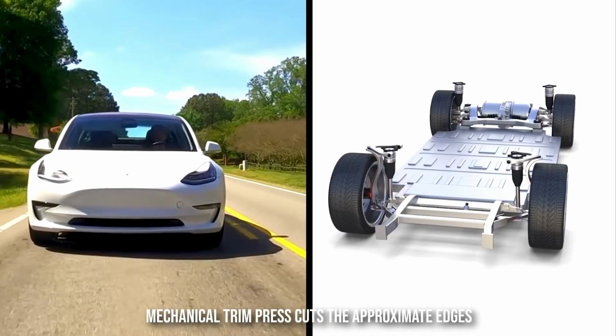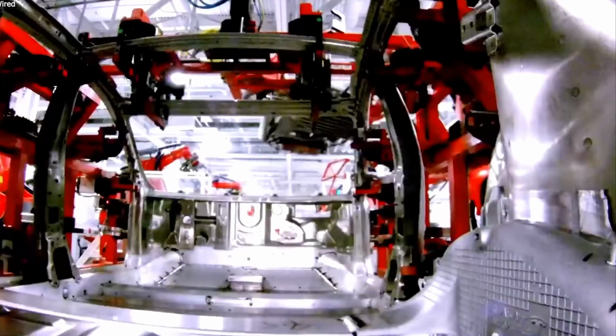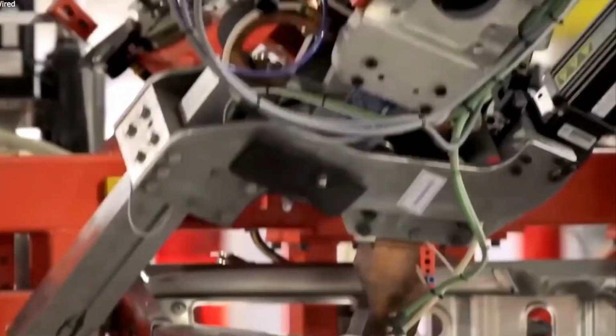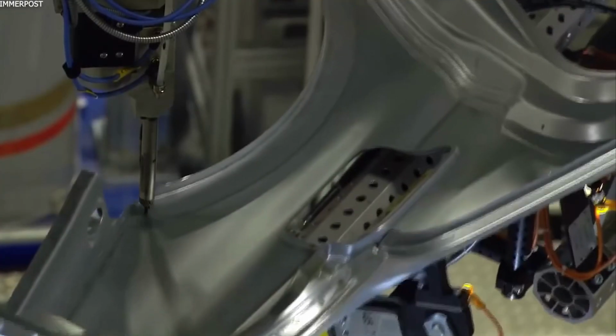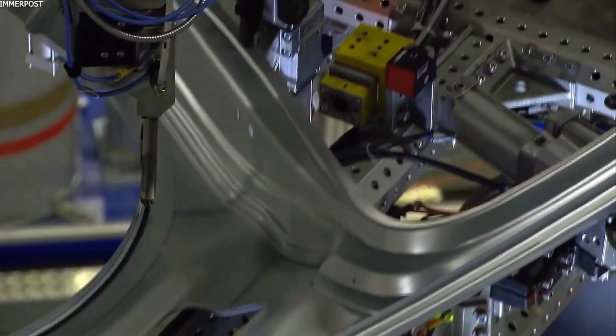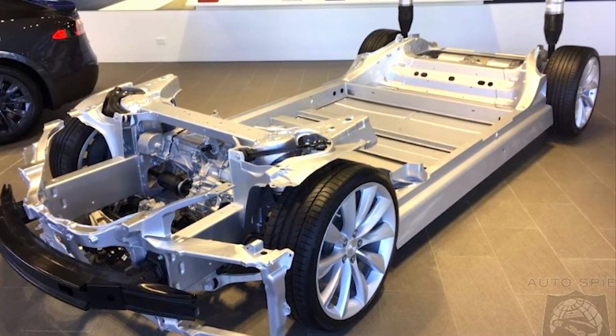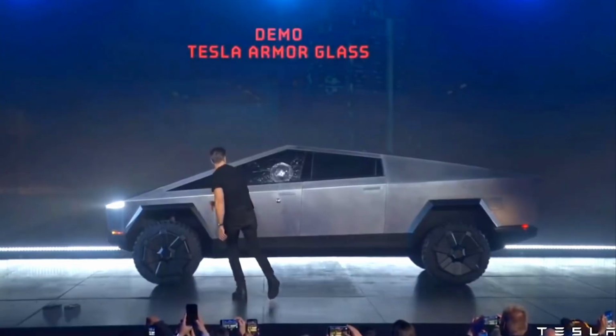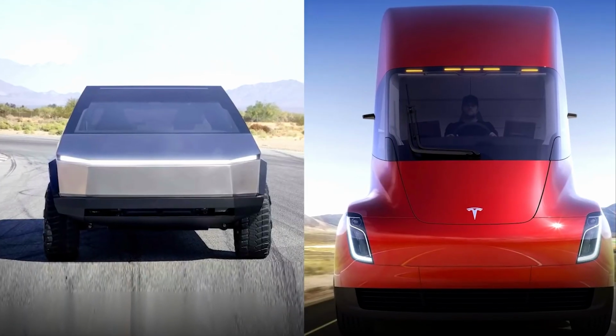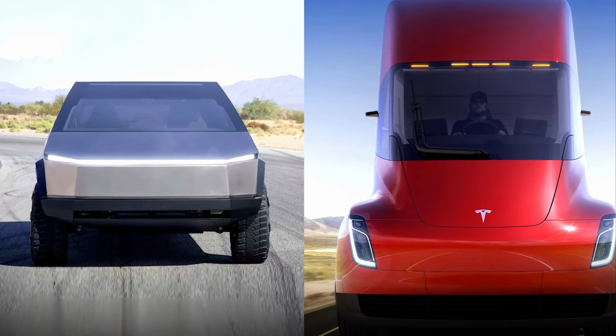A mechanical trim press cuts the approximate edges, with excess aluminum recycled back into the melting oven. The remaining helpful part of the casting is X-rayed to check the internal structure. It is then trimmed by laser, drilled for fittings, and then computer measured for accuracy. Reports show that the casting aluminum alloy used in the large Tesla chassis parts is primarily an aluminum-silicon mix with several other trace elements.